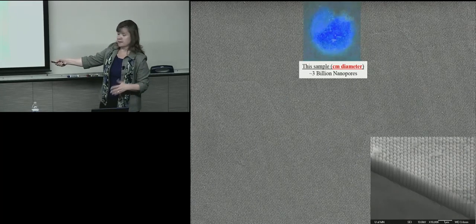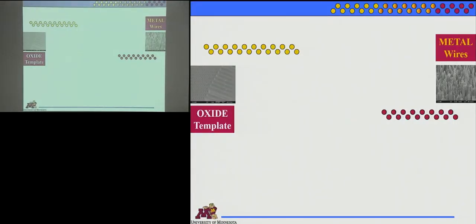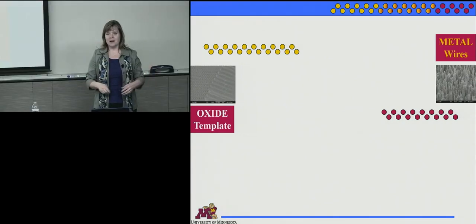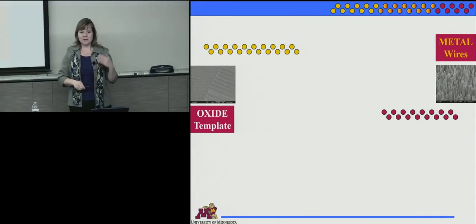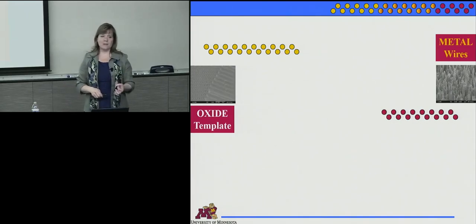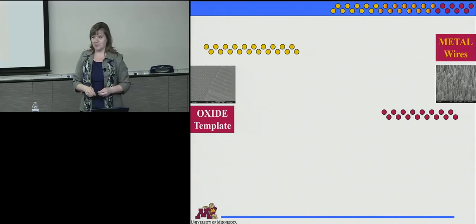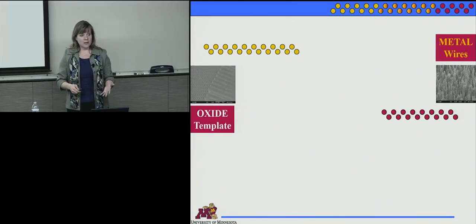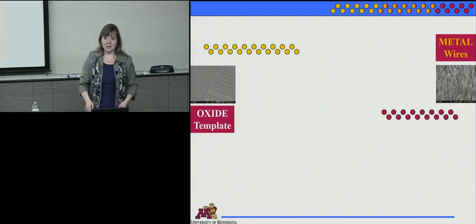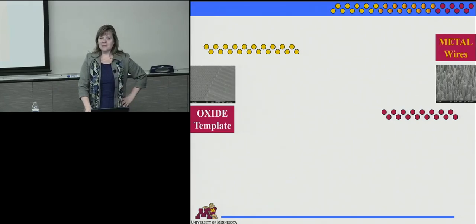And this is the side of that one, because if you grow on silicon, or if you just grow a thinner layer and anodize the aluminum to look at it, it won't be as thick a pore. I know people who make and sell 100 micron pores, so it's possible to go 100 micron with a 10 nanometer diameter. So I've seen 10,000 aspect ratio for a pore, and I just don't know anyone who wants higher than that. I think it could go on for quite a while, but by that point everyone says, great, give me the pore, give me the wire, and that's all they need. Okay, so that's the pores, yeah.